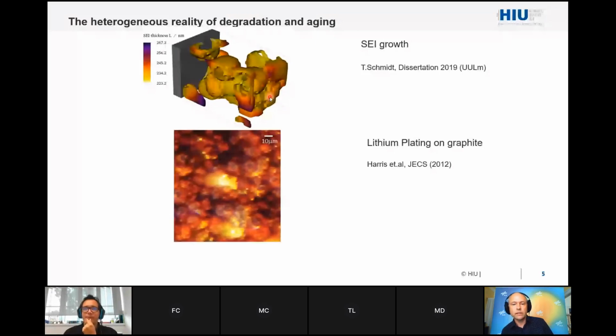And for the lithium plating, here is a famous picture of the Harris group, you see that plating is starting at several places. Here, this grayish part is considered to be the plated lithium. Red and yellow are different stages of charge on the graphite. So this is far from being really homogeneous across the electrode.